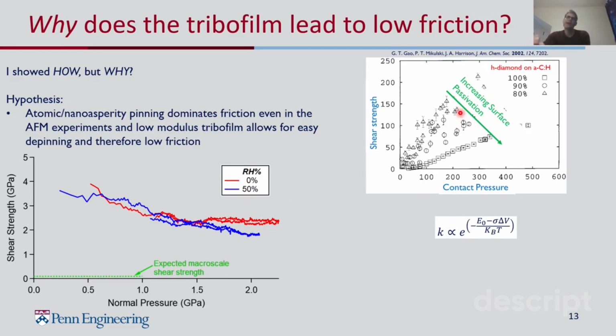So interfacial bonding is an Arrhenius type reaction, and actually we expect it to be stress assisted. So this gives you a simplification of the Bell equation here, where the activation energy to form an interfacial bond can be modified by an increase in stress, in this case, the normal contact pressure. And that reduces the activation energy, and therefore at higher contact pressures, you'll have more interfacial bonds per unit area, and therefore an increase in the shear strength. And so that's what they actually see here.